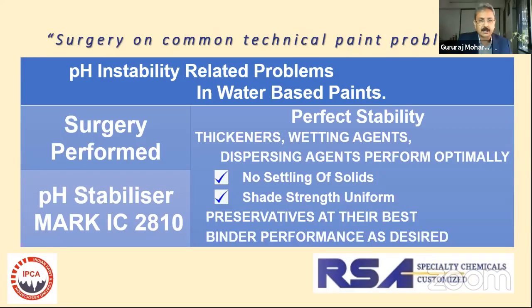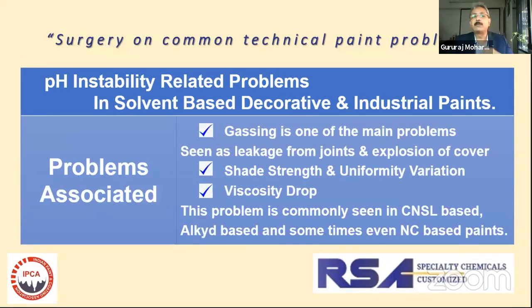Coming to the next, pH instability in your solvent-based paints. Basically in your solvent-based paints, the resins, the CNSL, alkyd, the resin systems, your pigments, they all tend to have a pent-up acid value, which tends to get released over a period of time in your system, and thus the pH of your system changes towards acidic. That's a possibility, a very good possibility.